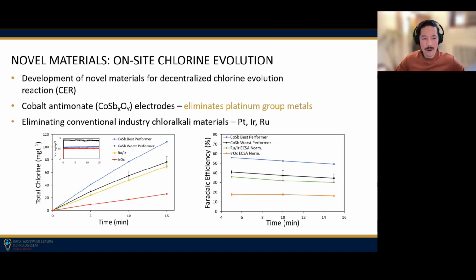But really the main one, and the one that is of interest to us, is understanding how much chlorine we actually make. So here is a graph of our best performing and our worst performing cobalt antimony electrode, our best performing in blue, our worst performing in black. And this was after a bunch of initial scoping experiments. And then you see here this gold or this yellow line is our ruthenium iridium electrode. So we got this electrode off the shelf from one of the main chlorine electrode manufacturers in the world. So this gold one was a specific electrode that's used in chloralkali processes. And you can see that our electrodes were exceeding that of the gold standard of chloralkali processes.